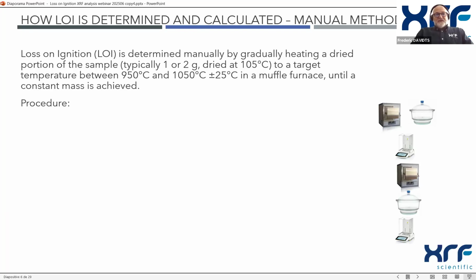So now, how is it determined and calculated in the manual way? The loss on ignition is made with a dried sample. We take 1 or 2 grams, and we set the temperature depending on the norms or the application, at temperatures like 950 up to 1050 degrees, plus or minus 25 degrees, in a muffle furnace.